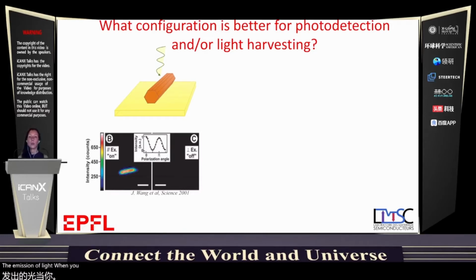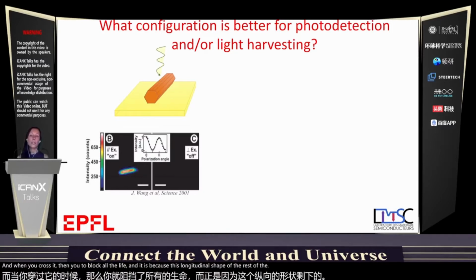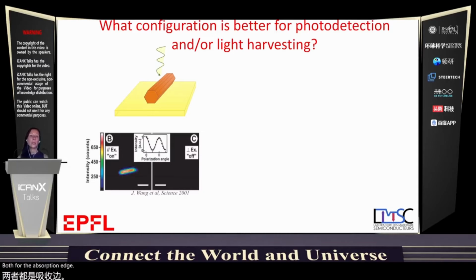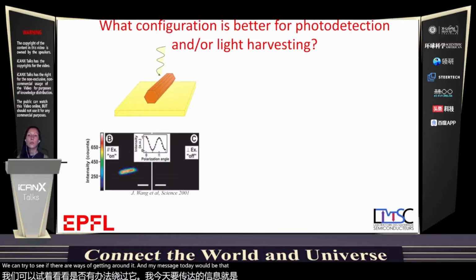When you have the polarizer along the nanowire, you have a lot of signal. And when you cross it, then you block all the light. And it's because this longitudinal shape of the wires makes it selective to polarization, both for the absorption and the emission. So you already see that you're losing half of the light. We can try to see if there are ways of getting around it. And my message today would be that you can use plasmonic structures to go around this.